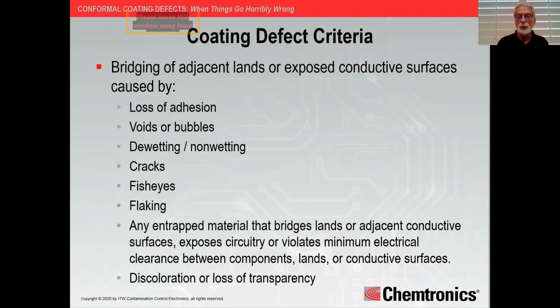Also, discoloration or loss of transparency. If a coating has been discolored by the environmental conditions, its surface environment, for instance, urethanes over time, if they're exposed to sun, have a tendency to yellow. If it hazes in any way, it's considered at least a condition to consider deeming it a defect. And the reason this is important is because the inspectors, the end users, if it's set up for rework, they have to be able to see through the coating for labels, markings, anything that they wish to inspect.